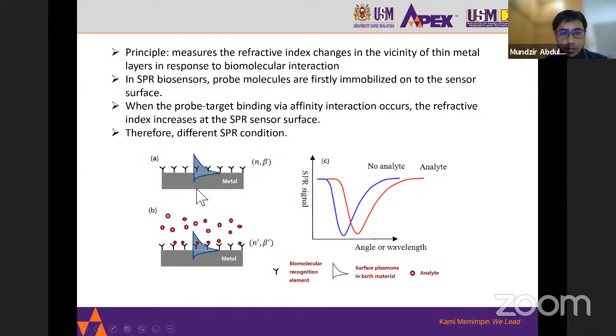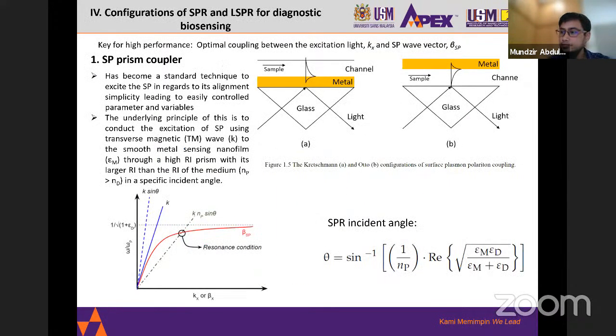So the A, which is without the interaction of biomolecules, the result is blue. It's no analyte. And when we introduce the biomolecules, the analytes, we can see a shift in the SPR signal because the resonance condition has changed. The resonance condition has changed because the refractive index at the thin surface layer, the interface between the metal and dielectric, has changed. So a different SPR condition, that is what we detect in our SPR sensor.